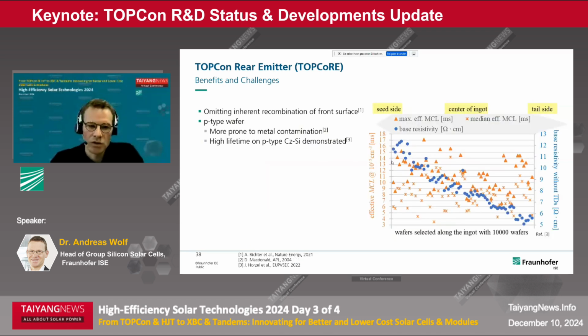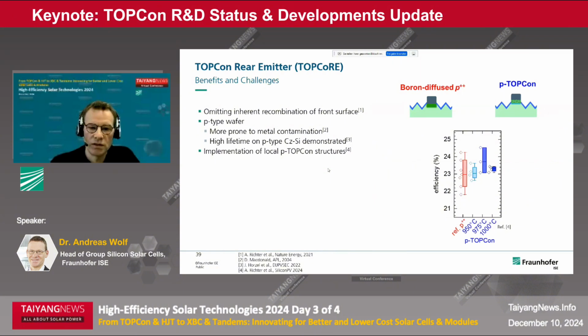Another topic for TOPCORE is switching to P-type wafers. It is known that P-type material is much more prone to metal contamination, so it's much more essential that you have a clean production, preventing contamination. On the other hand, we investigated industrial CZ materials that are already in the market, high resistivity CZ materials, which are suitable for TOPCon approaches and TOPCORE cells. And we achieved very high lifetimes here. So we think in principle, there's no limitation regarding P-type wafers to be able to provide also high efficiencies.